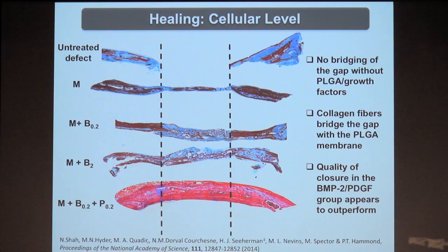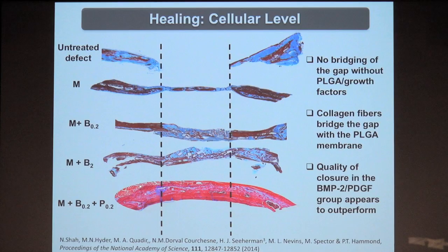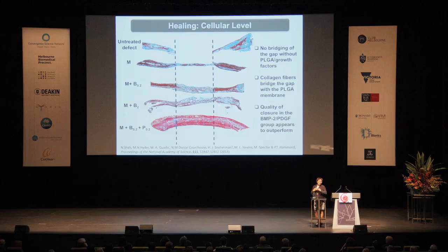And it turns out that the mechanical properties of this bone is equal to the mechanical properties of the native skull. So we can show that using this approach of sequential release in order, we can get a very nice, well-formed tissue that is difficult to achieve with just the BMP2 alone. And in fact, it's important to have these vessels form first before the tissue becomes so calcified that the blood vessels can't penetrate the bone.